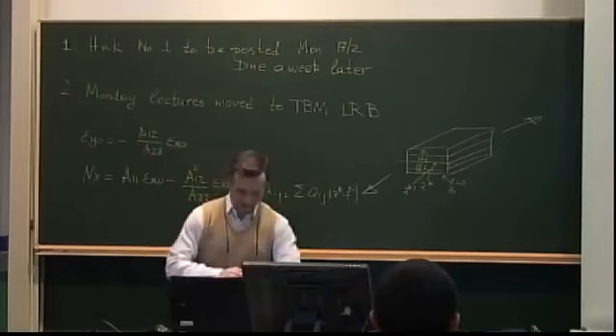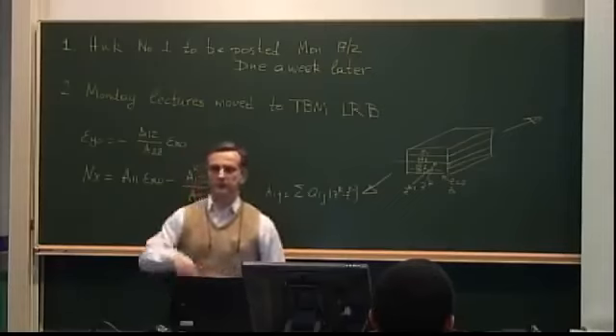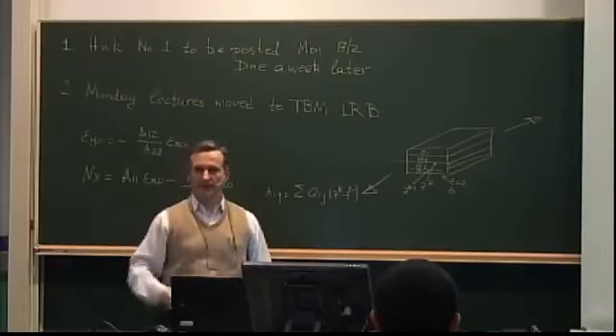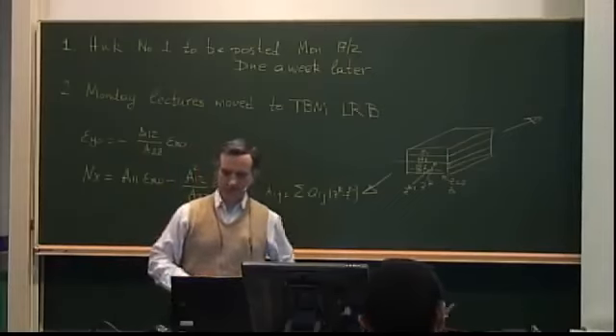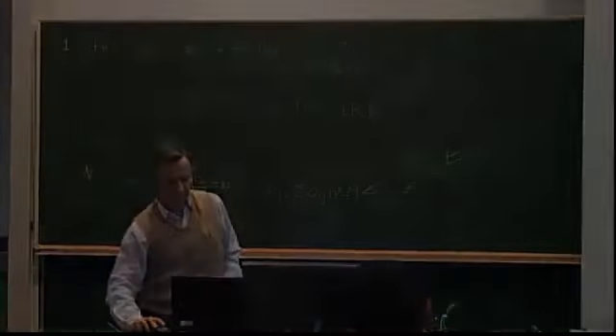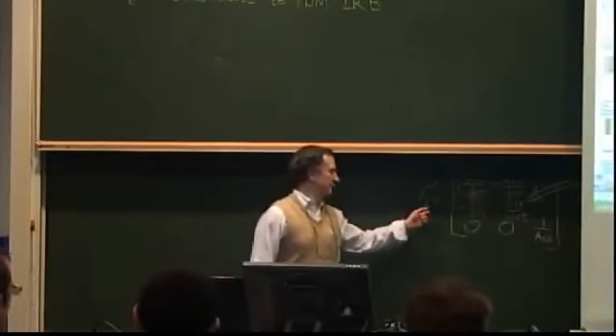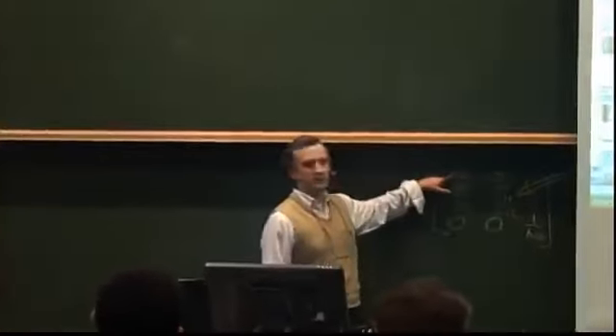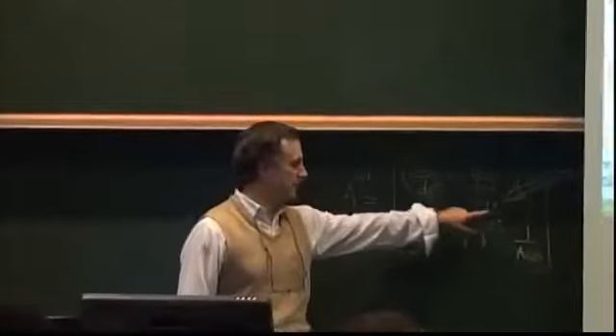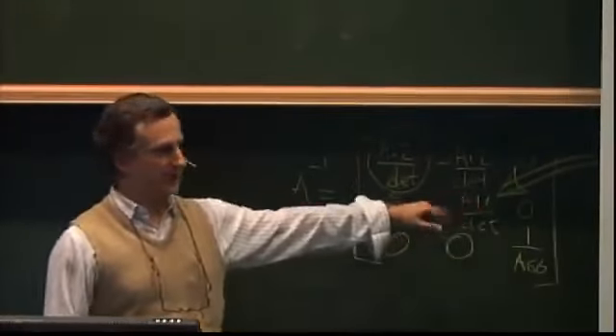So let's get into the failure modes of a ply in 15 minutes. That way we'll maintain the momentum. This is close enough to 15 minutes, minus half a minute. One correction, when I was writing the inverse of the A matrix, I had the A22 here and A22 there. This A22 is correct. This one was wrong. It should say A11. That's an oversight, thanks to the gentleman that pointed that out.